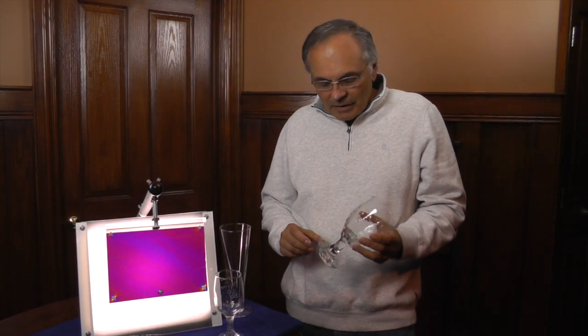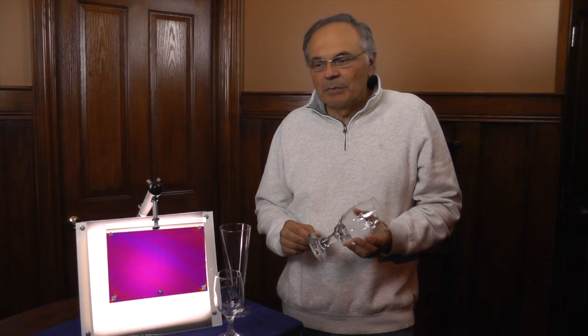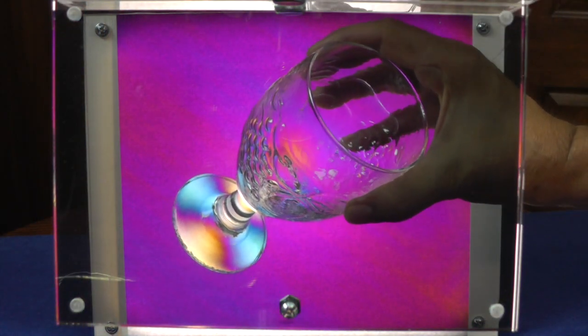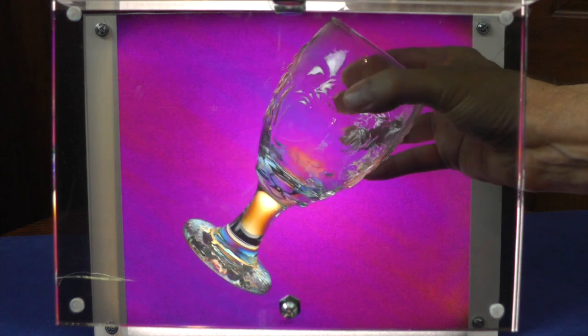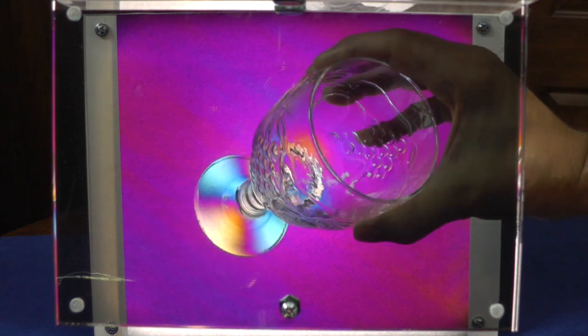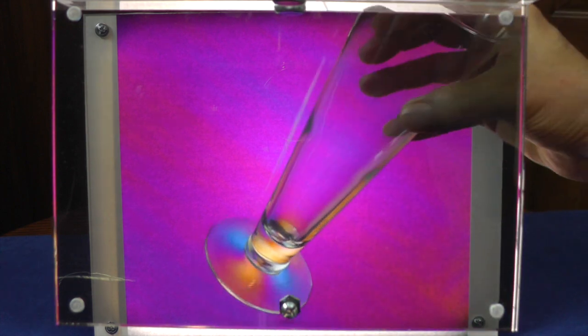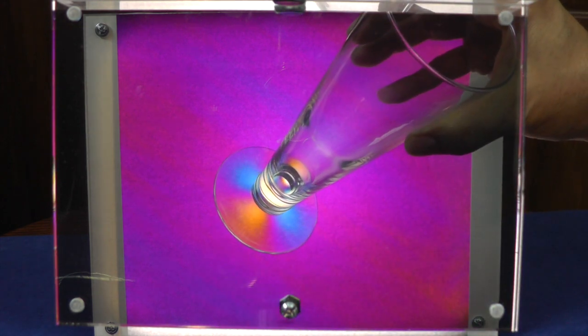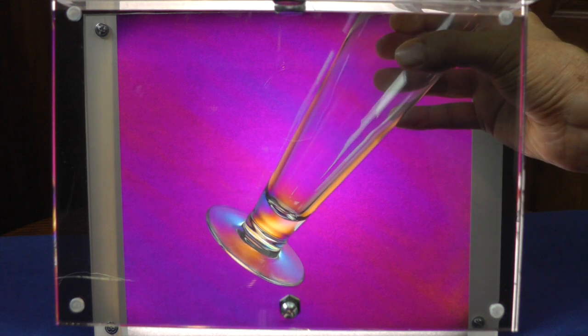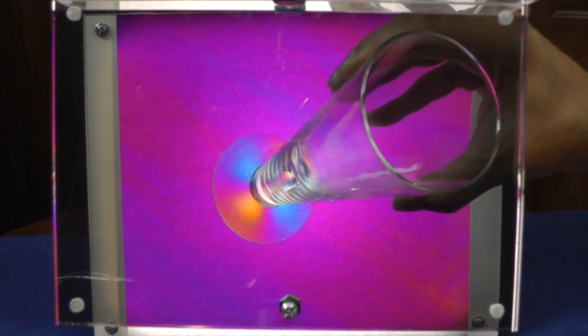All right, let's look at some commercially annealed glass and see what that looks like in the Polariscope. In this example of commercially annealed glass, you can see, again, there's a pattern. This would be considered light strain. You can see that the colors between the blue, the magenta, and the yellow is still a very soft transition. And this is acceptable in commercially annealed glass.